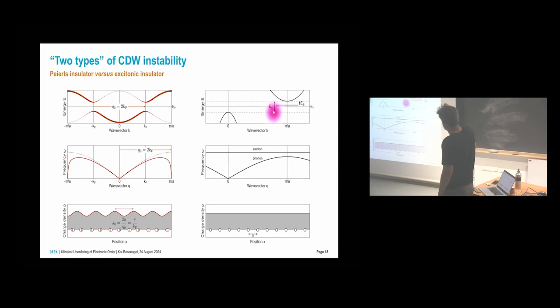It's smaller than the gap, but then through some mechanism you reduce the gap, so it becomes smaller and you get to a situation where the gap is smaller than the binding energy of the excitons. Then you have spontaneous condensation or formation of excitons, and this drives your exciton mode soft at this point. The exciton hybridizes with the phonon, and a hybrid exciton-phonon mode goes soft. This leads, again, to a static distortion of the electron density and the lattice.